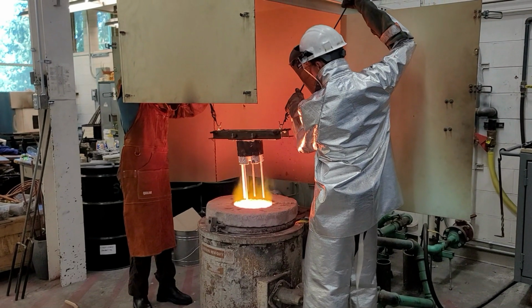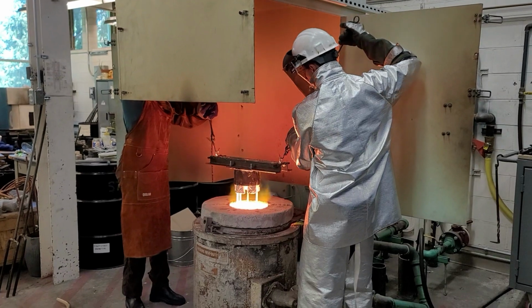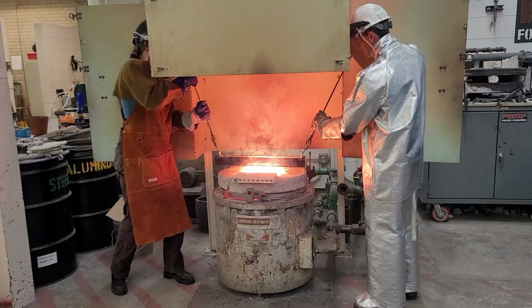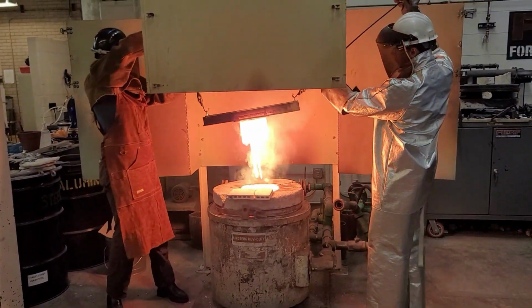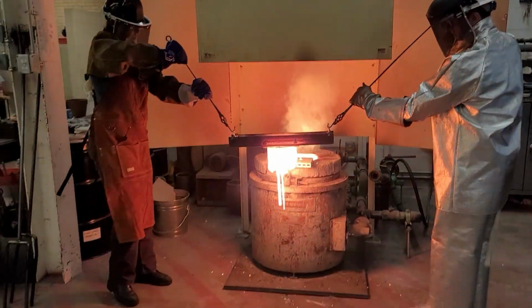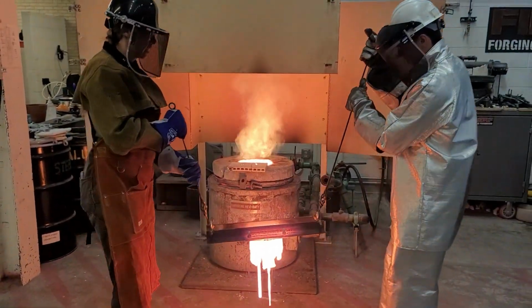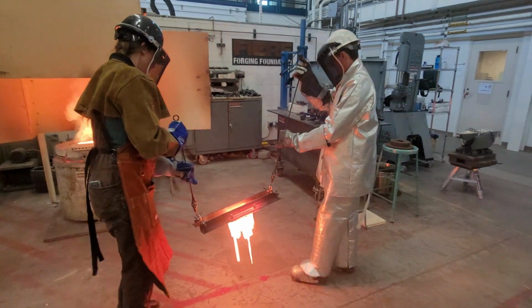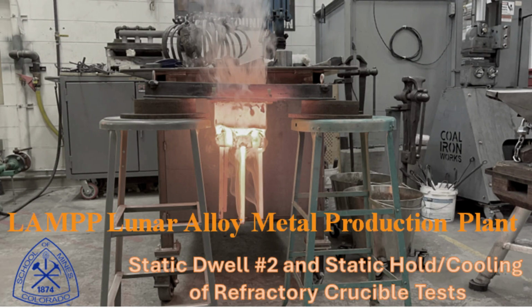These refractory materials will be submerged in a regolith melt with both anorthositic and basaltic compositions at temperatures of around 1300 degrees Celsius for durations of roughly 1 hour. The steel housing was custom designed in-house at the Colorado School of Mines.